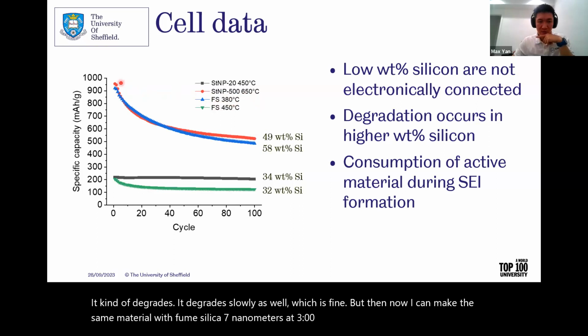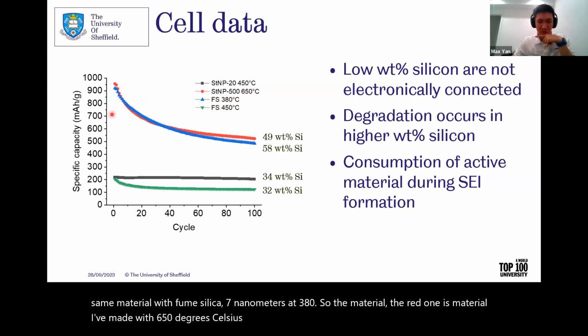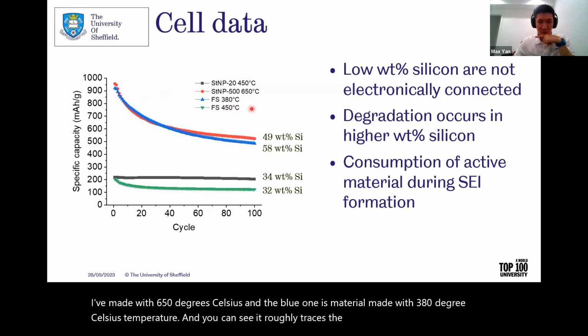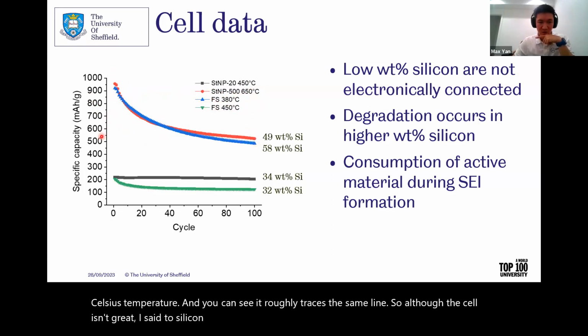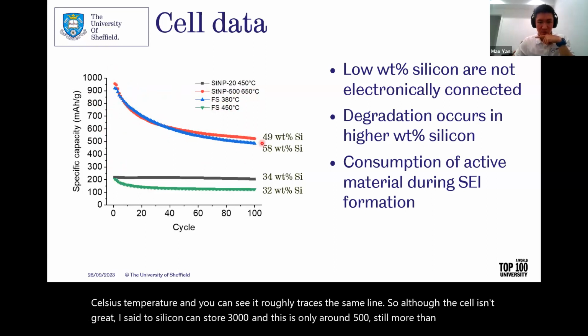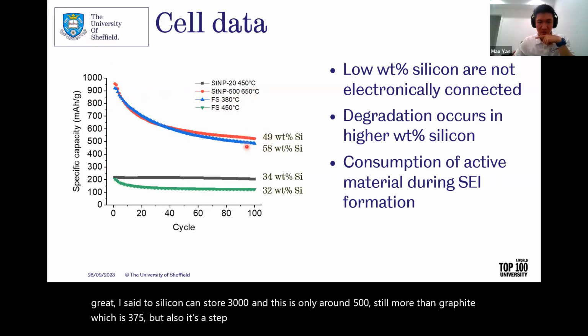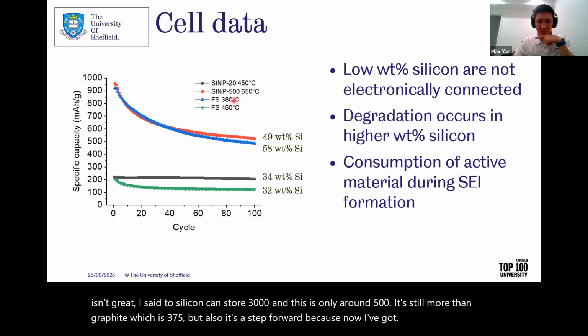So the red one is material I've made at 650 degrees Celsius, and the blue one is material I've made at 380 degrees Celsius. And you can see it roughly traces the same line. So although the cell isn't great, I said to you silicon can store 3000, and this is only around 500, it's still more than graphite, which is 375. But also it's a step forward because now I've got the same material, but I made it at a lower temperature.